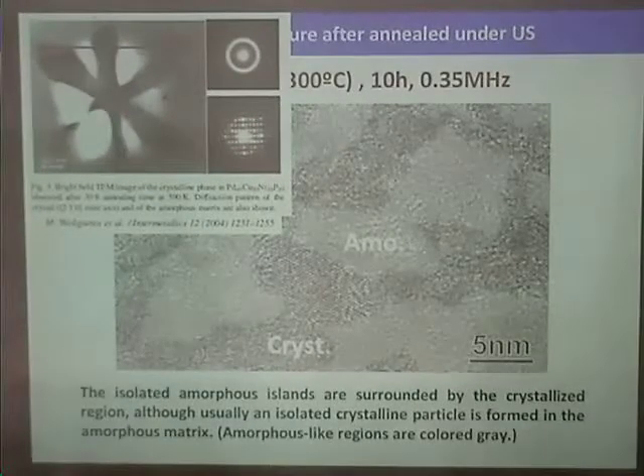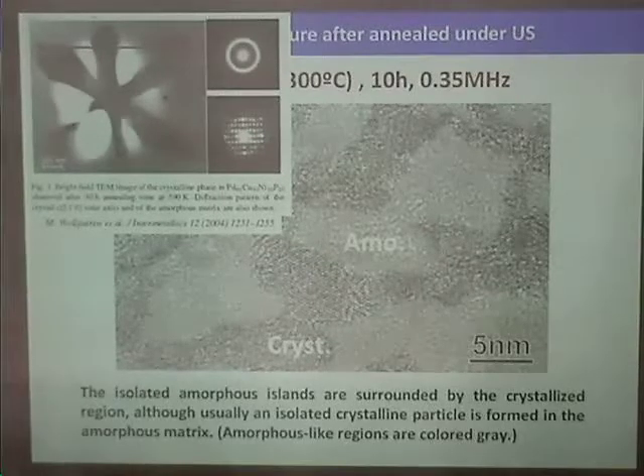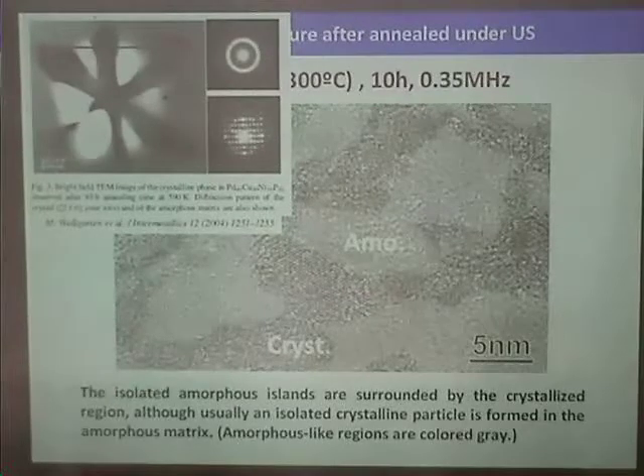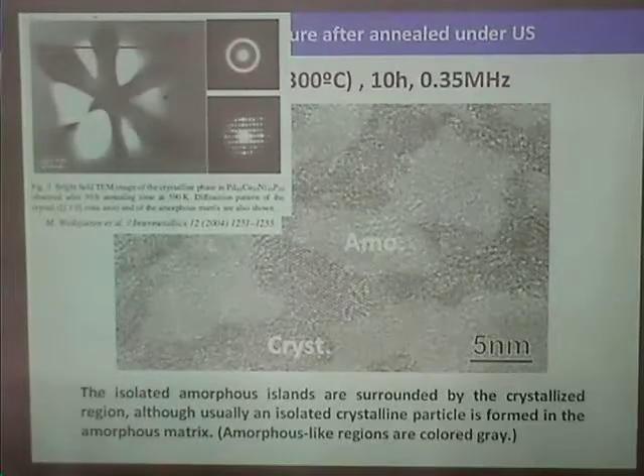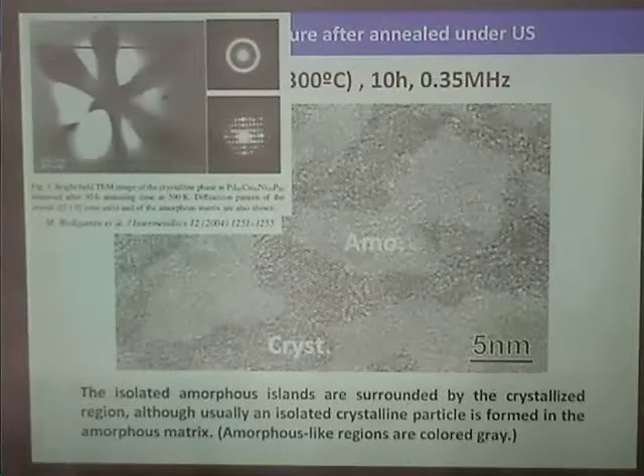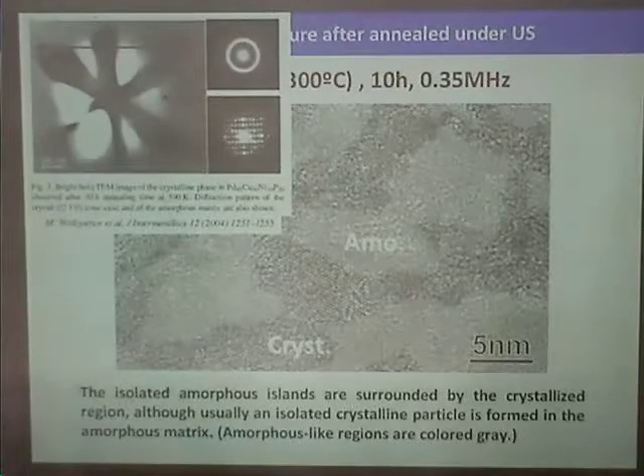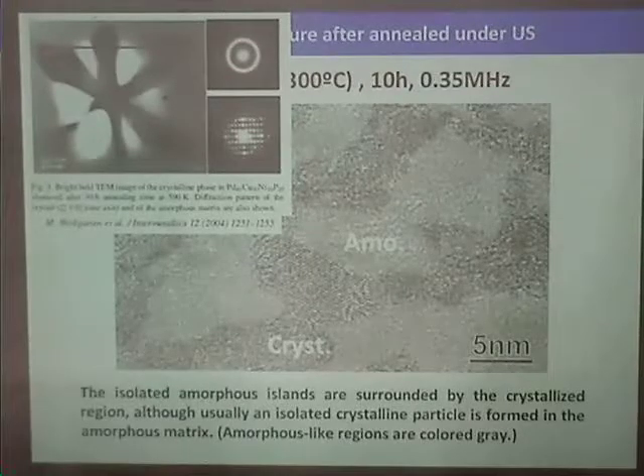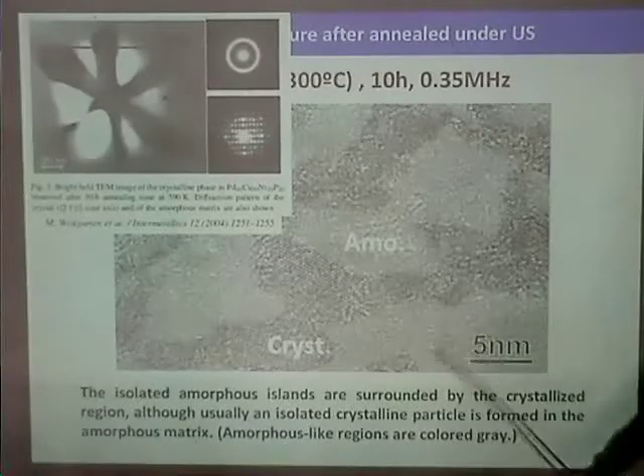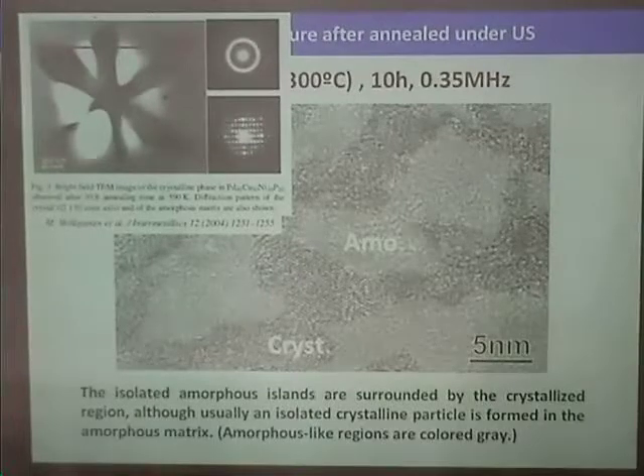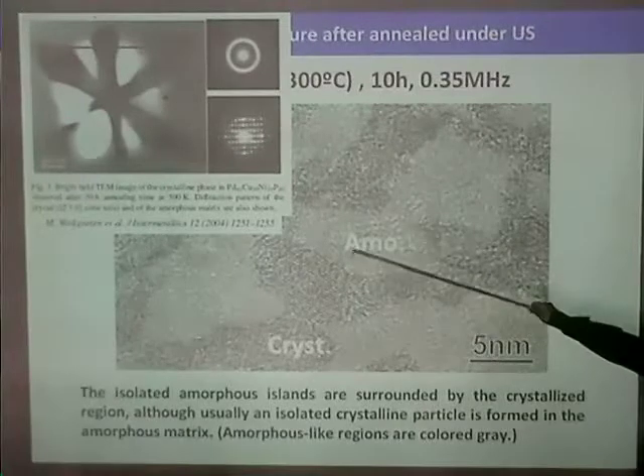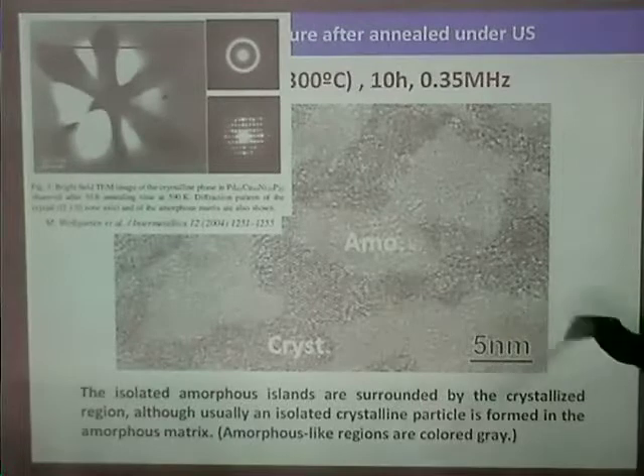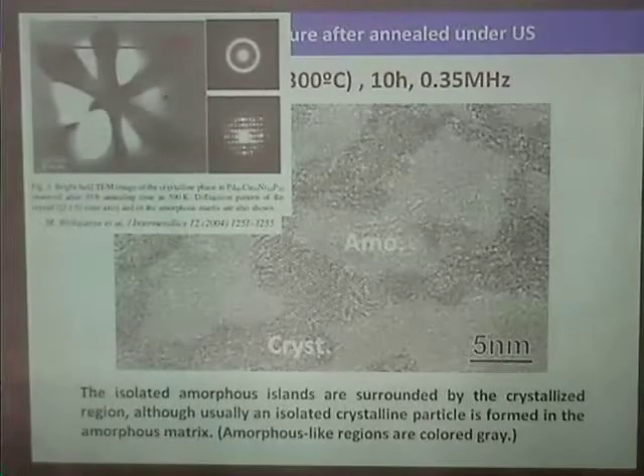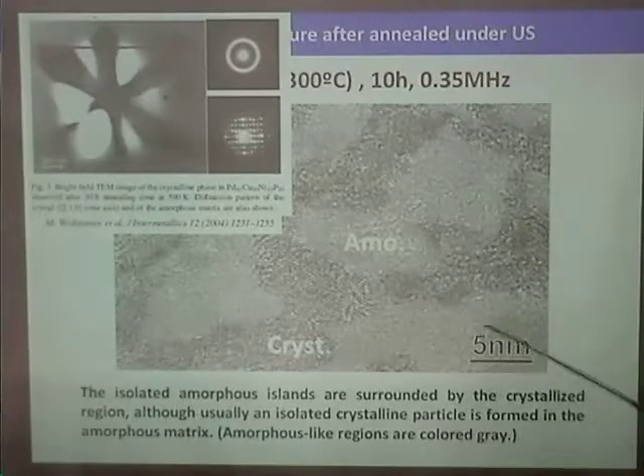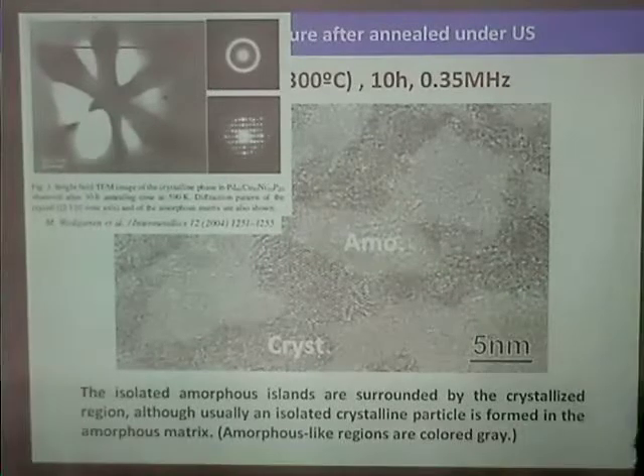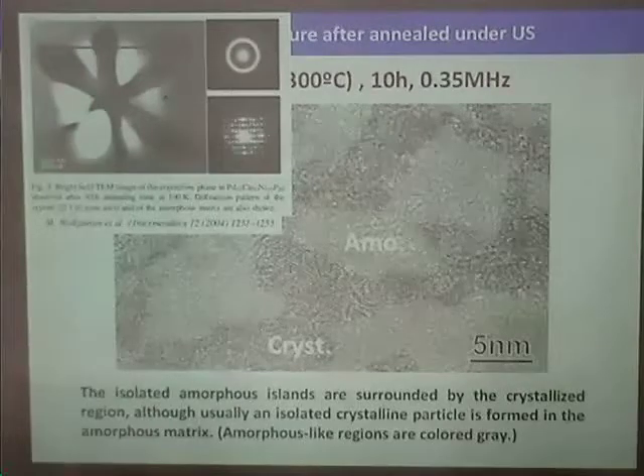Very naive question. In oxide glasses, it's rather usual to observe crystallization just after phase separation took place in a metastable state. Is it possible that some kind of phenomenon also happens in metallic glasses? This is a very serious question. I don't have an exact answer, but it depends on the system. In this case, the compositional fluctuation we have not yet determined. But phase separation has been seen in similar palladium-based glasses, so it is possible.